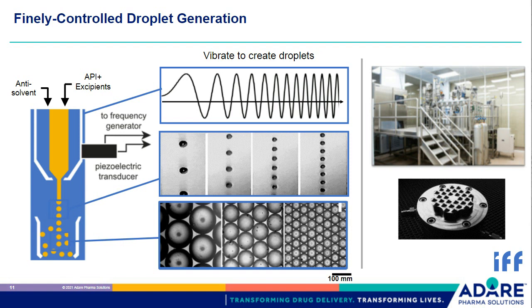This means that to create a 100 micron droplet, a nozzle orifice of 50 micron or less should be used, unavoidably leading to severe limitation of productivity and limiting also accessibility to low viscosity fluids, as well as increasing the risk of nozzle clogging. The Optimum nozzle, besides being equipped with a frequency generator able to precisely cut the fluid jet stream, leverages the effect of an annular stream that narrows and accelerates the nozzle jet to smaller than the orifice, which allows for small droplet size and minor impact on process output.